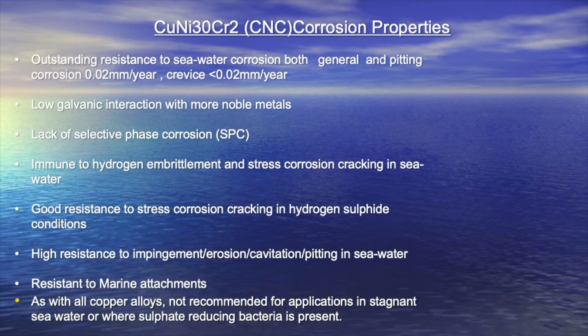So what does this mean? We can expect with these alloys in constant immersion of seawater, whether it's crevice or general corrosion, of less than 0.02 millimeters per year. These materials are also low in potential, which means that their galvanic interaction is normally excellent with more noble metals. There's no selective phase corrosion, so the rate at which the corrosion occurs is consistent, unlike some other alloys where they can be variable. There are a range of other additional benefits as well.